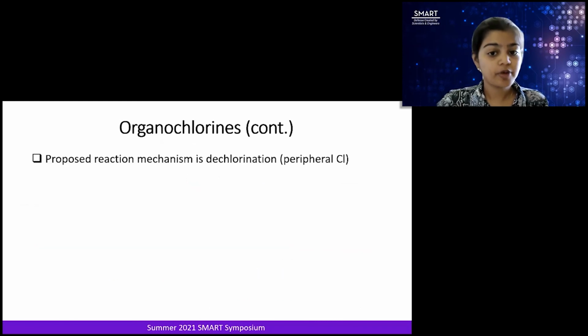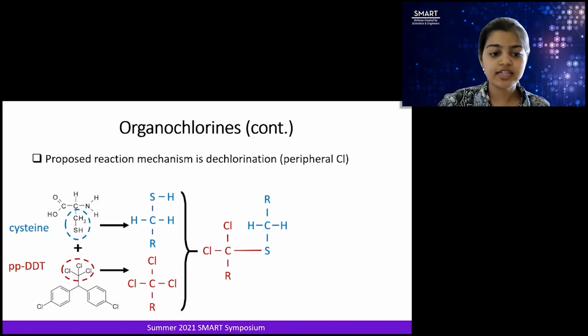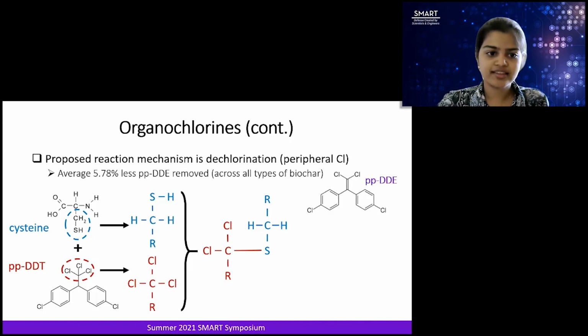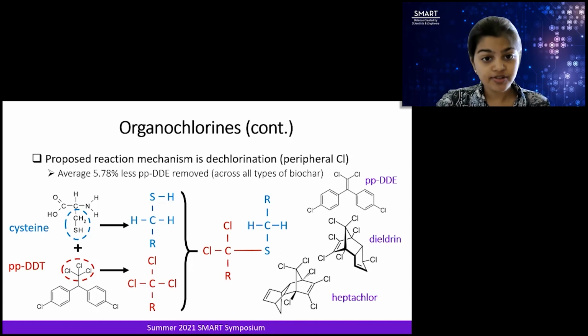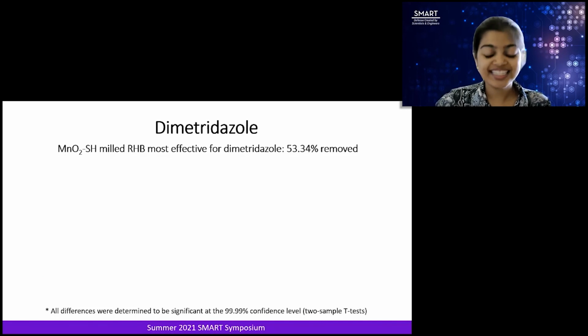From this, we can see the proposed reaction mechanism might be dechlorination of the peripheral chlorines. Cysteine and PPDDT would interact, and one of the chlorines would replace the hydrogen group on the thiol. This is also in line with an average of 5.78% less PPDDE removed across all types of biochar compared to PPDDT. PPDDE has one less peripheral chlorine, so it makes sense that the less chlorine there is, the less likely it is for this reaction to occur. This proposed reaction mechanism could further be used to sequester other more deleterious organochlorines as well, such as dieldrin and heptachlor. Next, let's look at dimetridazole.